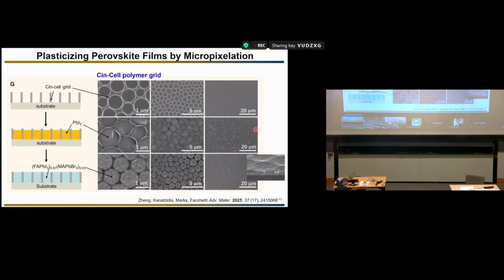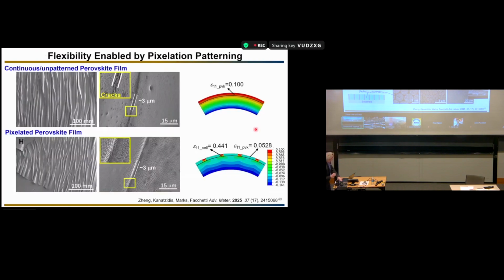We're using a 2-step process. We first fill the holes with lead iodide, and then using the metal halide and organic halide you want to use, you create your perovskite composition. What you see here, which is quite neat, is that the perovskite likes to grow only in the holes of the polymer. So you're basically creating a matrix in which the holes are filled by the perovskite. And when you do that, and you do the process on parylene, you can make perovskite films which don't crack.